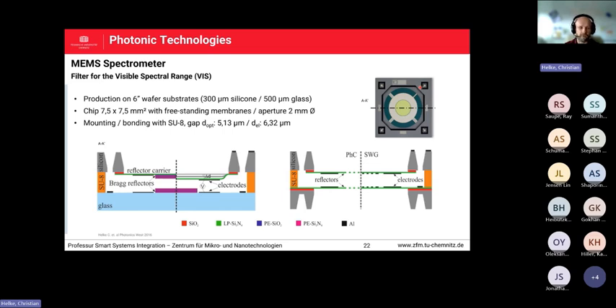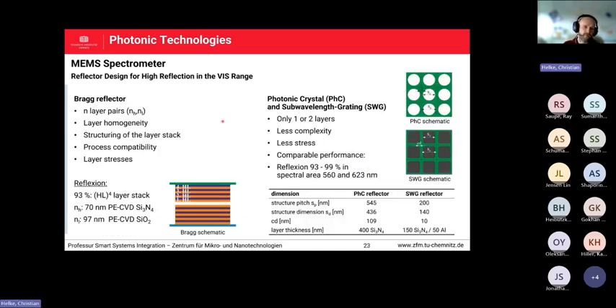This slide was already shown by Carla before, and I will now focus more on the white part, meaning the nanostructure integration into the thin silicon nitride membrane itself, or the metals on the silicon nitride, in comparison to the Bragg reflectors. I guess some of you know that one can use the Bragg reflector itself as a reflector concept. All of them consist of high and low refractive index layers as layer pairs, with some requirements for the complete technology flow and integration in wafer level processes, because you have to ensure layer homogeneity, you have to ensure the structuring of the whole layer stack, the layers you need to integrate have to be compatible with the wafer handling process and everything there, and you have to deal with layer stresses of every single layer.